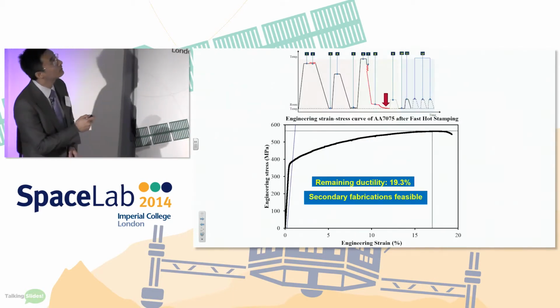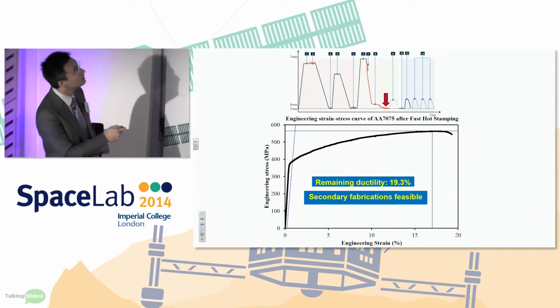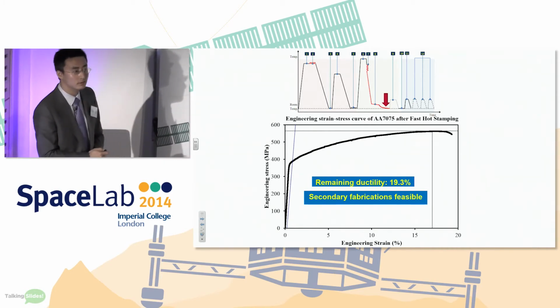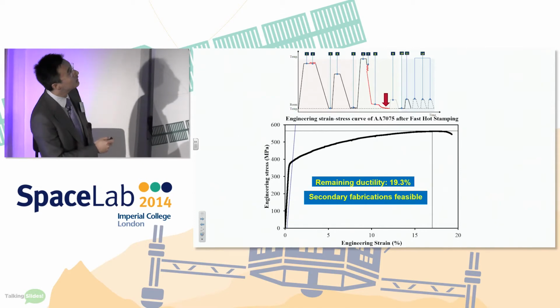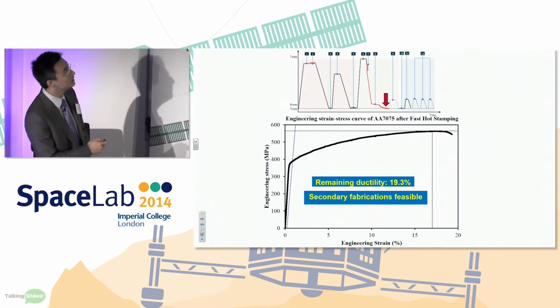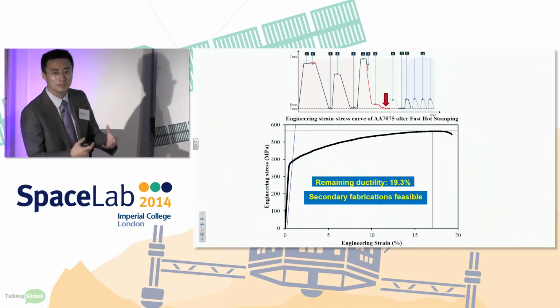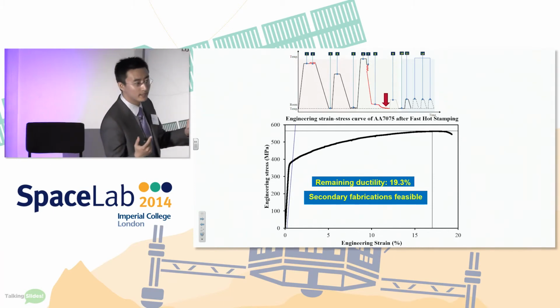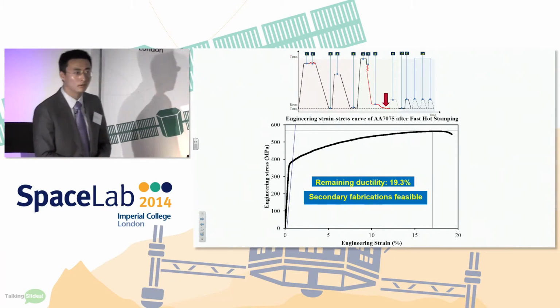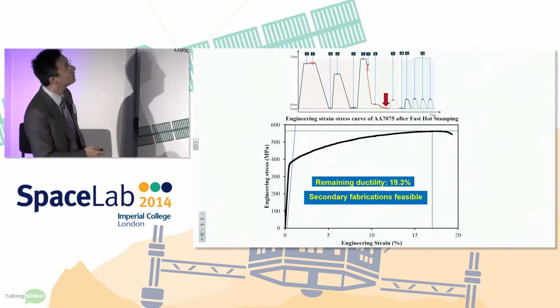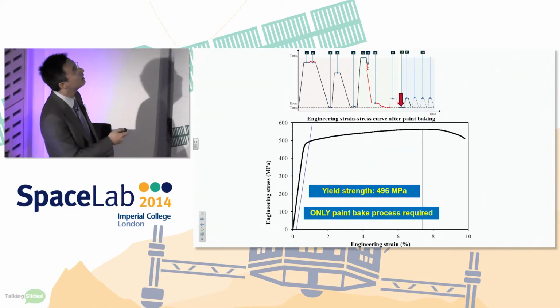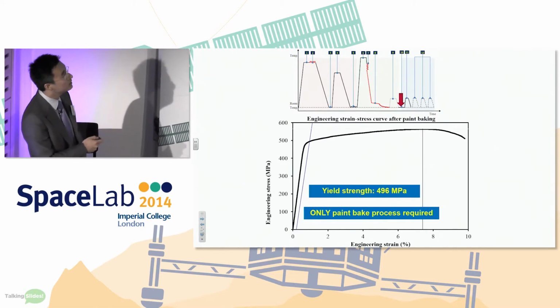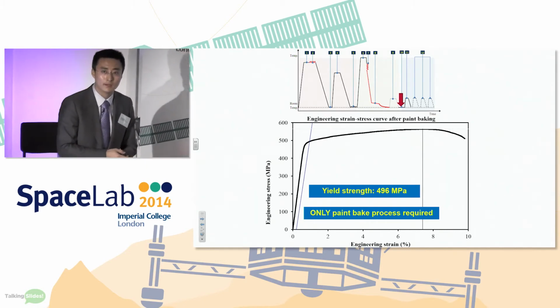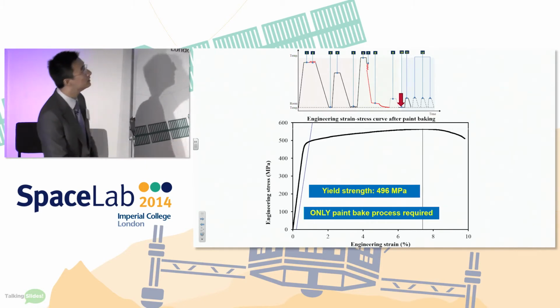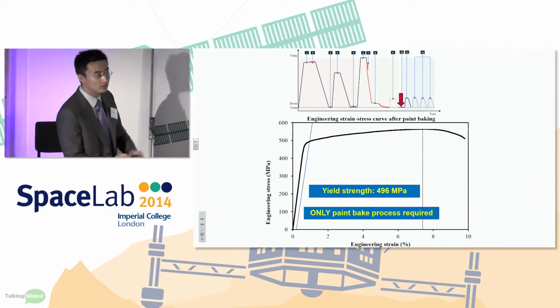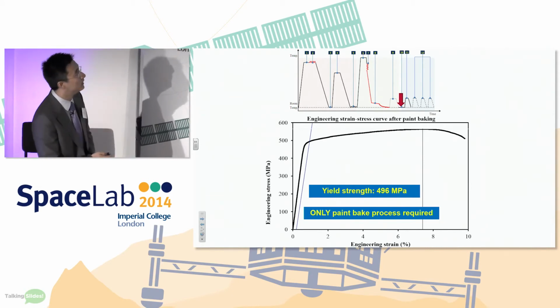And immediately after fast hot stamping, we can see this is the tensile stress-strain curve. So the part is very ductile. The remaining ductility is about 20%, which means you can conduct something like hemming, bending, or self-piercing. That's possible. And after the aging process, we can achieve nearly 500 megapascals in the component. So it's very strong, and we don't need an extra artificial aging process.